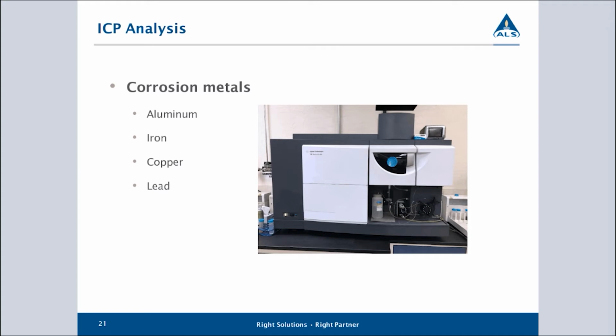We do an elemental analysis mainly for the metals. We can also look at some of the additive chemistry directly. So the main elements that we're monitoring are things like aluminium, iron, copper, and lead. These are the metals that are most commonly found in cooling systems. And if we see an increase in any of these elements, it is an indication that corrosion is taking place in the system. So even if all the other properties look good on the coolant, if these are increasing, we have corrosion. There is something causing corrosion within our cooling system.